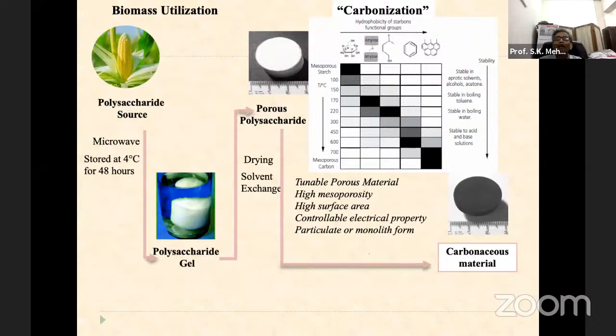This is in the University of York, the Institute for Green Chemistry is there, and they are working in this type of area. So the idea was to have biomass utilization. The polysaccharide source was taken, and using microwave at 4 degrees for 48 hours, you can create polysaccharide gel. And further on, you can dry it, you have solvent exchange. Then from this polysaccharide, you can create carbonaceous material.